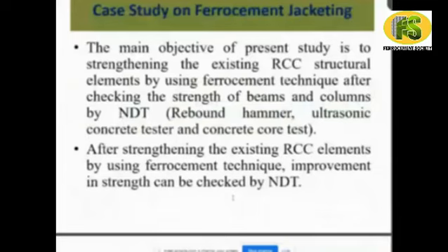Case study on the ferrocement jacketing. The main objective of the present study is strengthening the existing RCC structural element by using the ferrocement technique after checking the strength of the beam and column by NDT, non-destructive testing, Rebound Hammer and ultrasonic concrete tester, and partly destructive testing, that is the concrete core test. And after strengthening the existing RCC element using the ferrocement technique, the improvement in strength can be checked by NDT tests again.